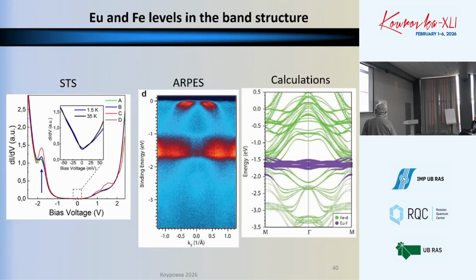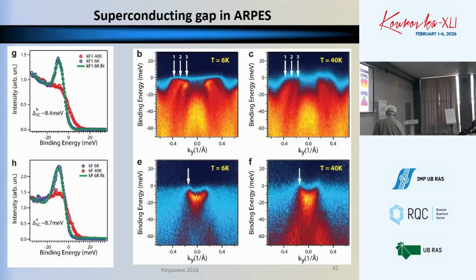Also verified by scanning tunneling spectroscopy in dI/dV. You see here a feature which is explained by the density of states in this almost flat band. So everything is clear, and then it's interesting to see how the superconductivity develops, using ARPES measurements. We can trace the development of the superconductivity, how the gap changes, how the gap opens at any specific point of the Fermi energy. And I have a movie, but maybe I will skip it.